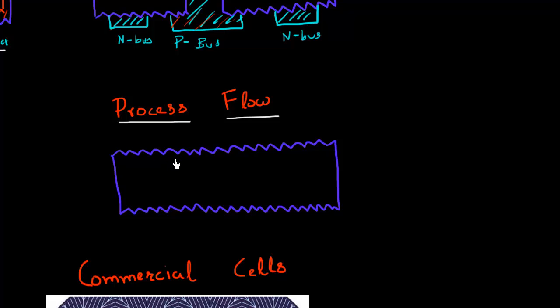But one way to do that is to start with the conventional cell process flow. So you perform this texturing by acidic or wet etch. And then we perform this diffusion similar to the way we would do in a conventional cell. So we have this N plus diffusion on the top and we started with a P wafer. And now what is done is you drill holes. So you drill holes now and you drill this hole towards the cell. And you essentially form this hole and these vias are over here.